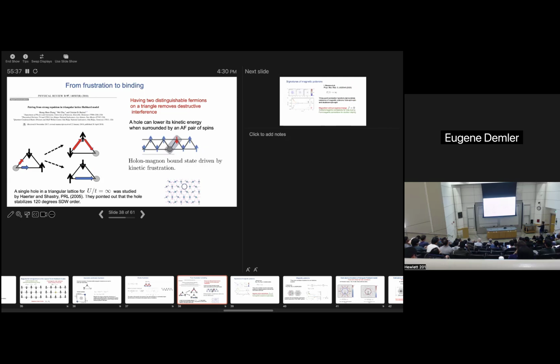A related argument was given earlier by Haerter and Shastry when they analyzed the U equals infinity limit for a triangle, in contrast to Nagaoka's regime, and they found that the lowest energy state corresponds to the configuration we would find for anti-ferromagnetic interaction, when spins make this 120 degree structure.